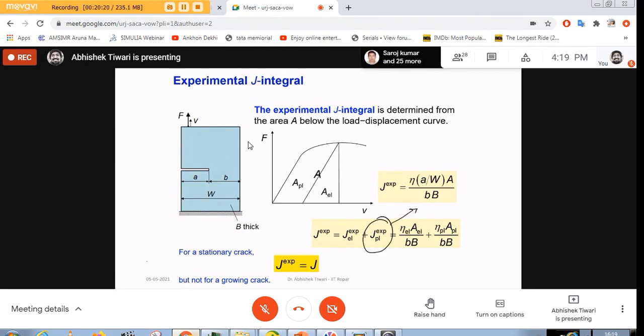The problem here is that this part of the J integral is not available for the crack tip. If the crack has to move, this energy cannot be used. This energy is permanently taken by the material, and the material will not give it back. Only this elastic energy, which is stored, is available. When the crack needs to grow, it needs some amount of energy, and that energy can only come from the stored elastic energy. We are also counting plastic energy, and that's the problem.